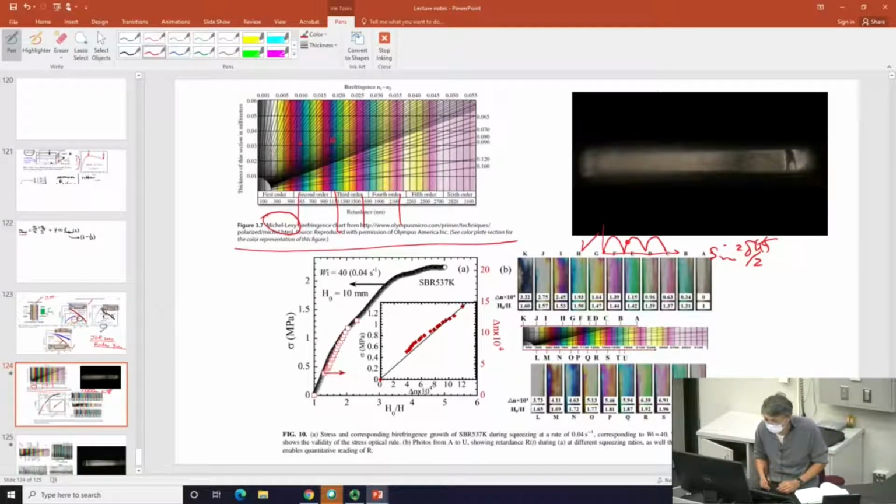As I mentioned before, if you have a lot of birefringence, you tend to be in this saturated region. There's no information about the variations. Remember, this is a beautiful technique if you have spatial variations, because there will be a color distribution allowing you to claim that you have seen birefringence of different levels spatially across a certain region. Since we are going to produce a lot of birefringence, you would quickly reach a saturated region.